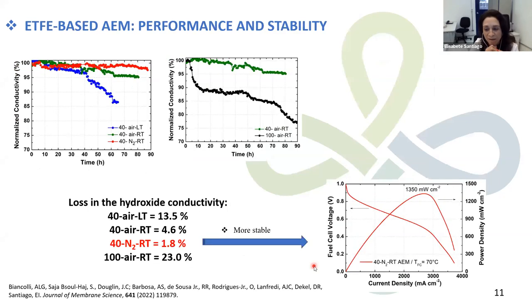Okay, in terms of performance and stability, you have observed that the material obtained at 40 dose rate, nitrogen, and room temperature presents the lowest hydroxide conductivity loss, just 1.8%. It's more stable and the performance is very nice. The performance is as high as 1350 milliwatts per centimeter squared. So we have published this paper, and you show it is possible to have a ETFE AEM with very nice stability and very good performance combined.